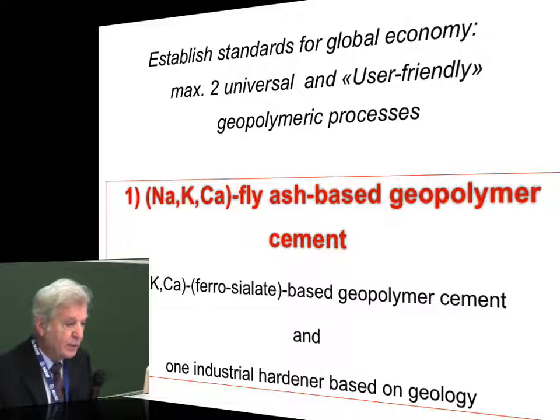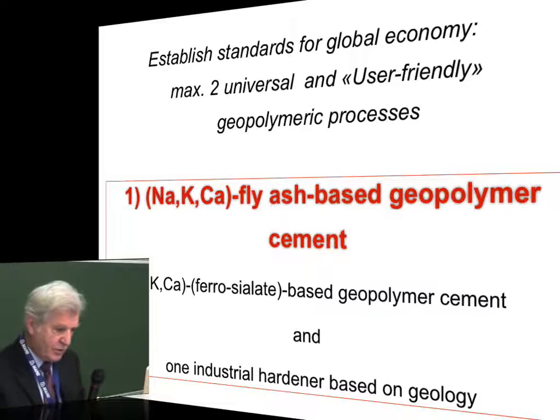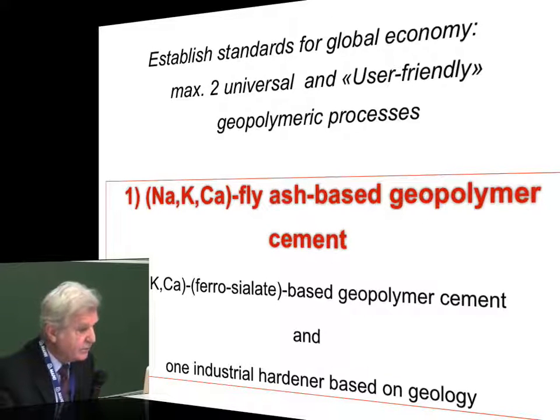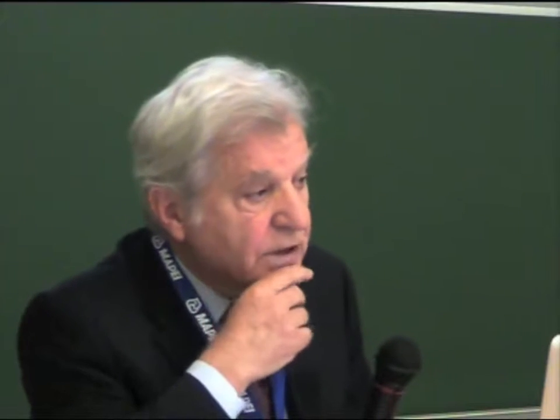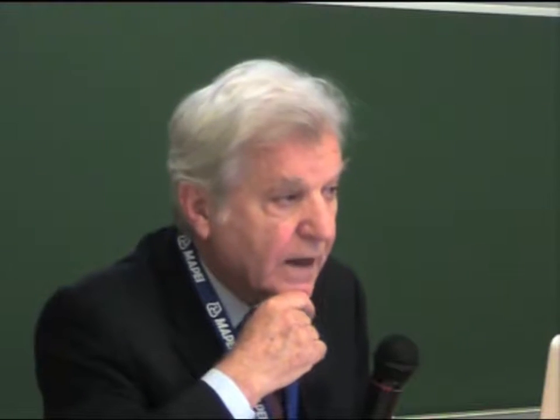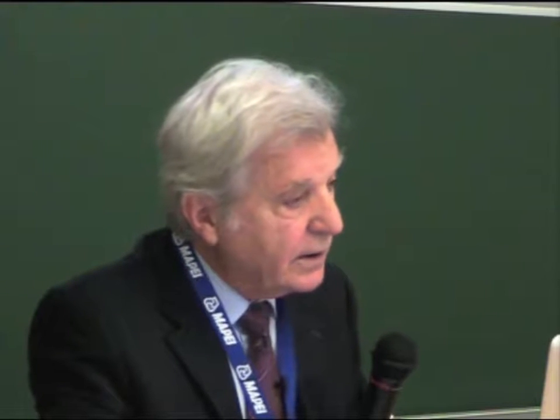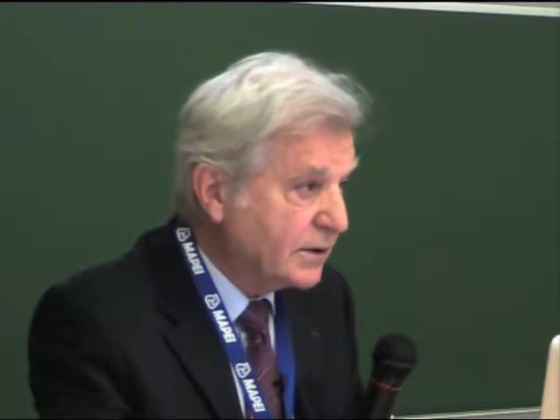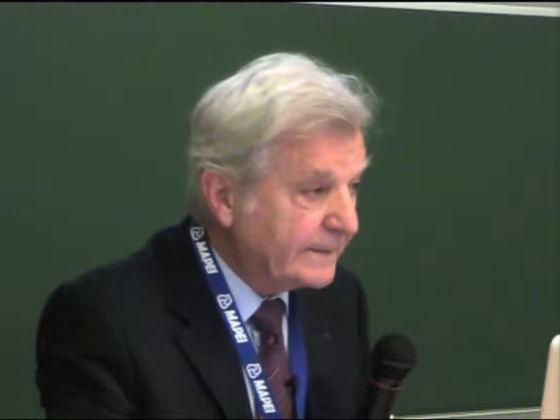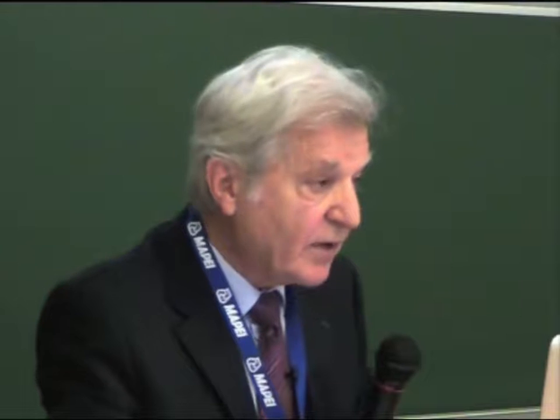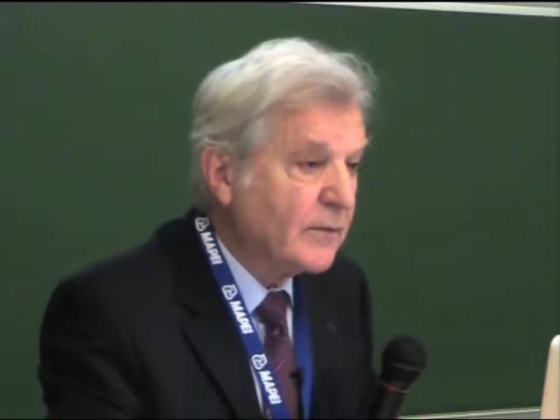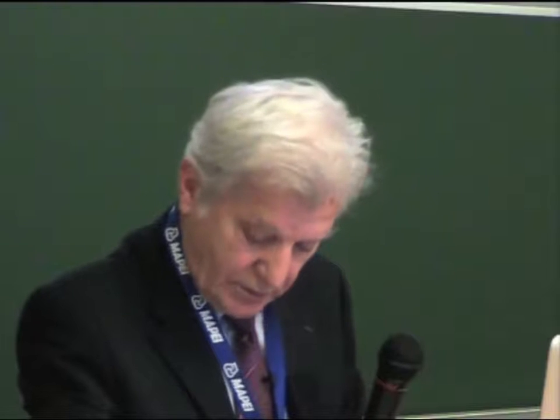So let us come back to the standards. First, sodium, potassium, calcium based fly ash based geopolymer cement. I always was skeptical about fly ash, and I only studied fly ash in the years 2005, practically 20 years after starting geopolymer cement. We had a European project that I was involved in, and I started to look at it. For me, fly ash was not a relevant material in terms of raw material for geopolymer cement.